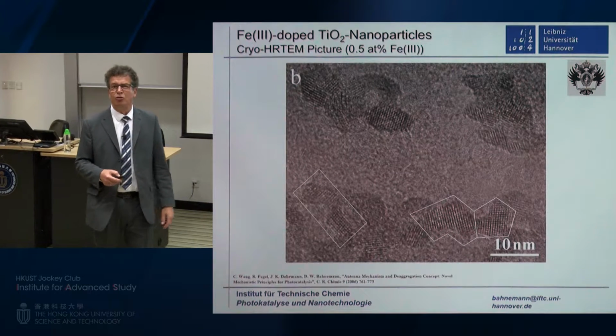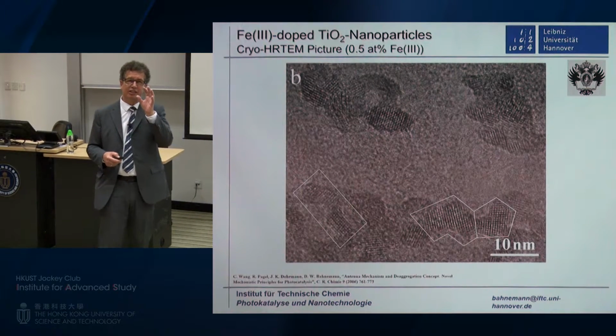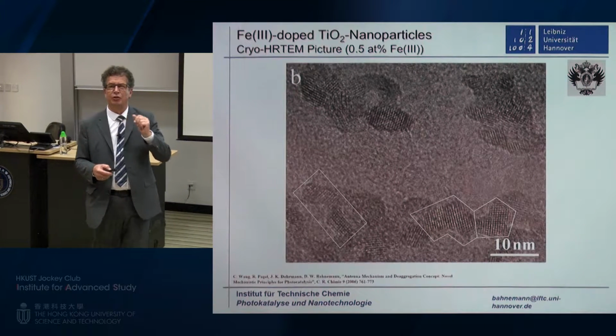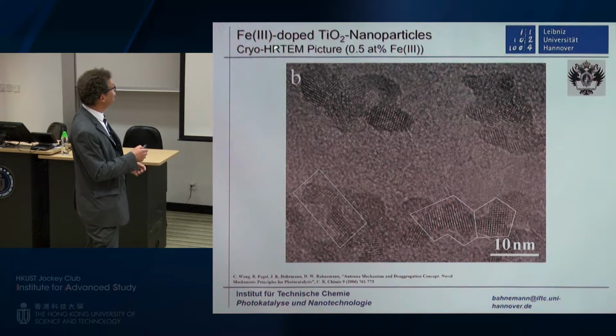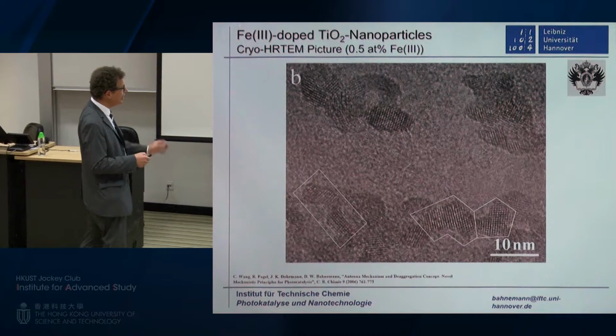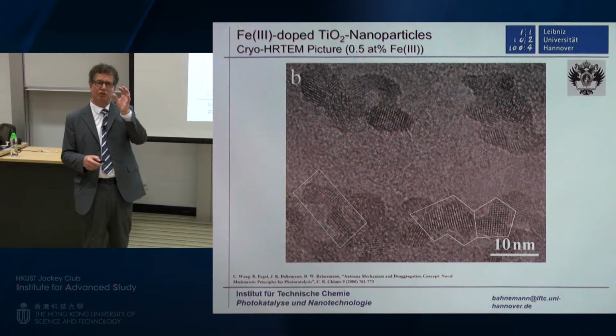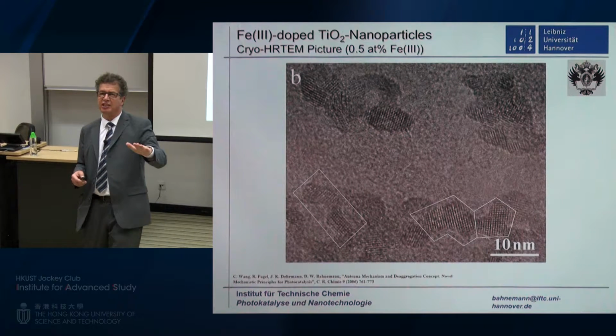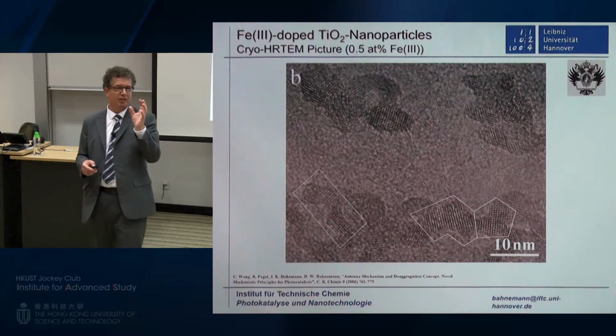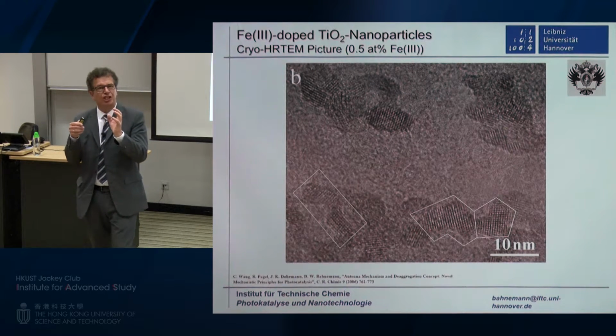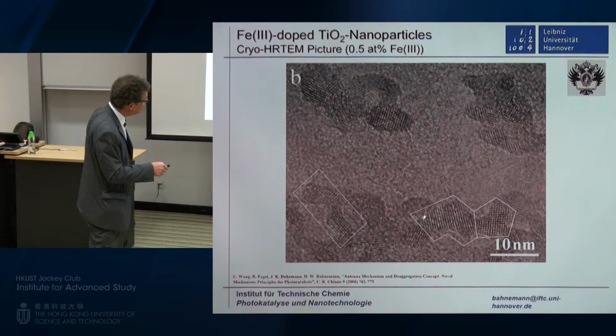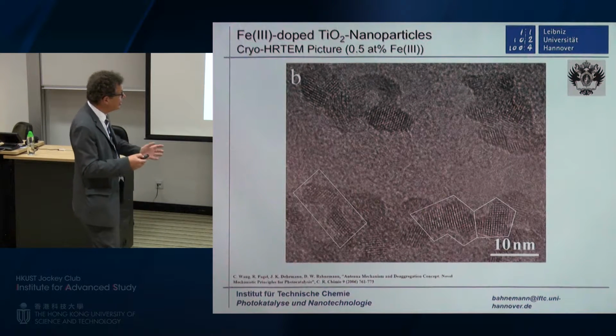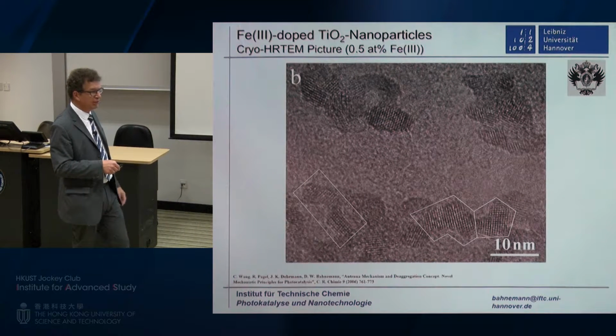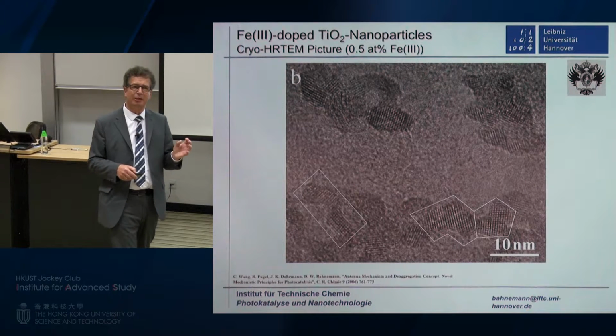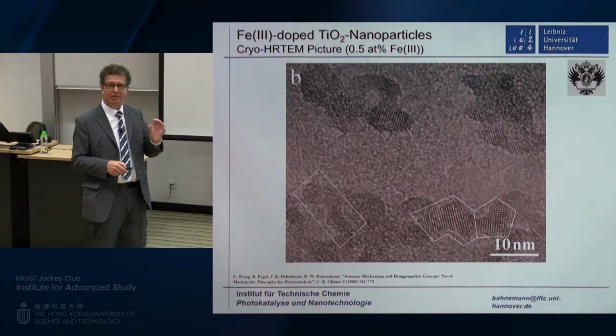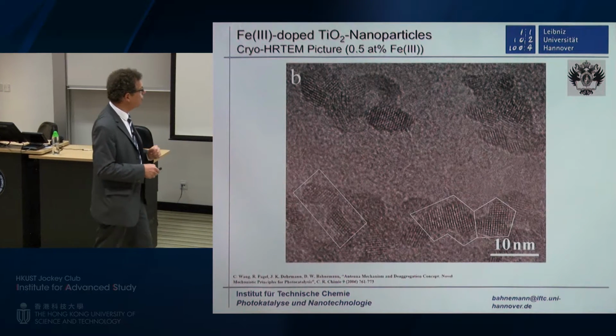However, already looking closely into a photocatalytic mixture, if you try to look at the nanoparticles, you use high-resolution electron microscopy. These pictures were done using a cryo system, which means you are deep freezing your system as quickly as possible with the aim to retain its geometry. If you then look into the system, you see these nanoparticles and the atomic planes, and you see these are already little nanocrystals. These crystals, by the way, have never seen any temperature exceeding room temperature. So you can form single crystals at very low temperatures without any problem.